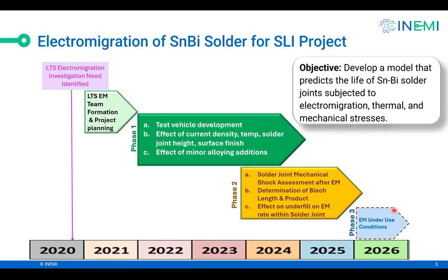And then phase 2, which I think we are going to talk about today, has to do with the solder joint mechanical assessment after electromigration, because bismuth is a very brittle substance, and that's the biggest issue with tin bismuth solders. And also determining the Blech length and product, which is the thickness, and at small lengths you get a lot of backflow and back pressure, and electromigration stops, and we want to determine what that is for tin bismuth solders. And also underfill effect, there has been a couple of papers published about the underfill effect on these tin bismuth solders, and we want to use our technique, which PJ is going to go over, to determine that.